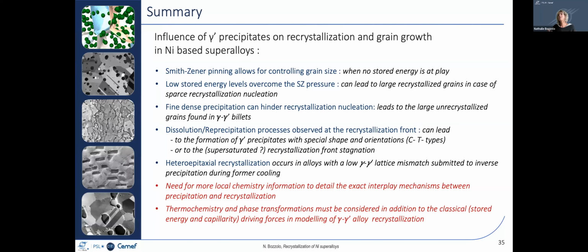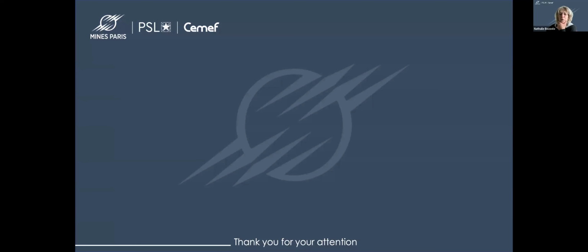So basically, in the summary, I wanted to emphasize a few points about the end of the lecture, where in these alloys, we have found a number of recrystallization phenomena which have quite strong interplay with precipitate evolution and phase transformation phenomena. And therefore, for these particular types of nickel-based superalloys, I don't think we can develop suitable recrystallization models without also describing concomitant phase transformation. That's it. And with this, I would like to thank you for your attention.